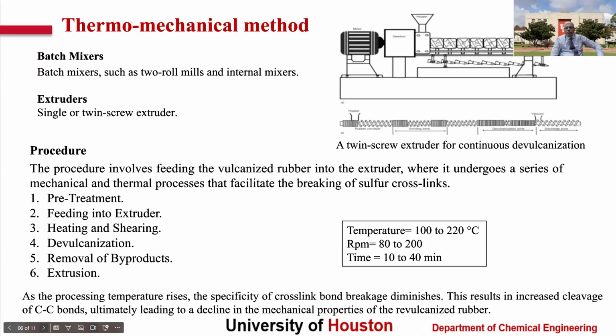And you can use, for example, a single screw or twin screw extruder, which is shown on the right-hand side here. The procedure is: first you have to get the pre-treatment, then feeding into the extruder, heating and shearing, devulcanization, and then you have to get the products out of it, and then extrusion. The whole process is an extrusion. The typical temperature is 100 to 220 degrees centigrade, RPM 80 to 200, and time is 10 to 40 minutes.